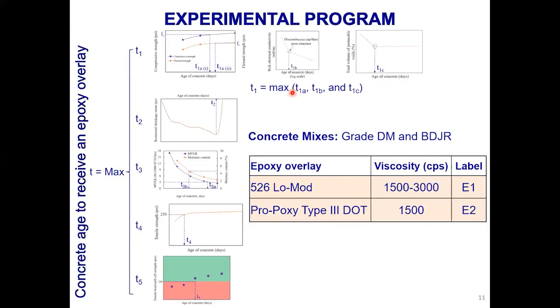So in order to do that, first we have to understand the parameters that are going to influence the performance of an overlay, or in other words, the application time of an overlay. So first thing, concrete, we need to cure it, but we need to look at strength as well as the durability. So in that case, strength is one parameter we typically evaluate, compressive strength. And then we had to look at when it's going to develop a discontinuous pore structure with the smallest volume of permeable voids to have a durable deck. So we were looking at all three parameters to decide on the concrete curing duration.